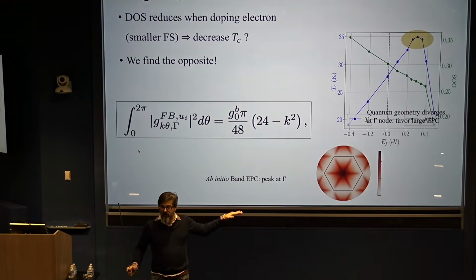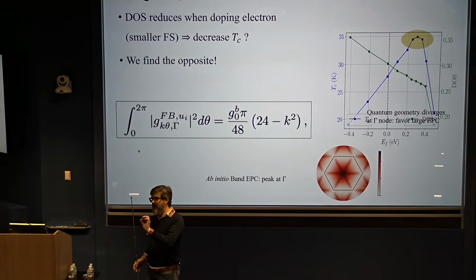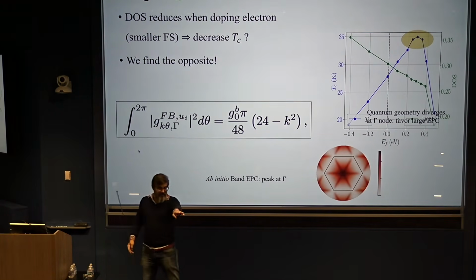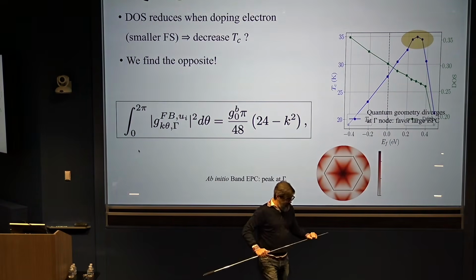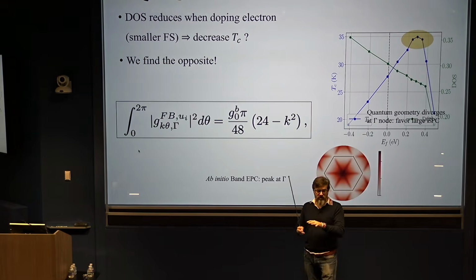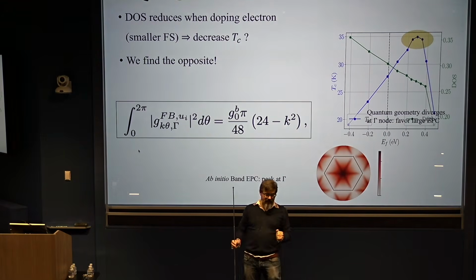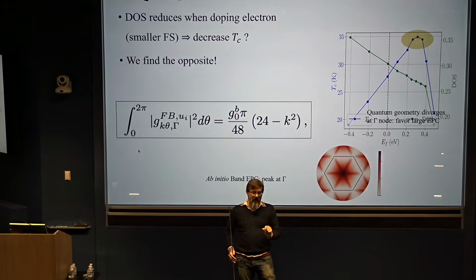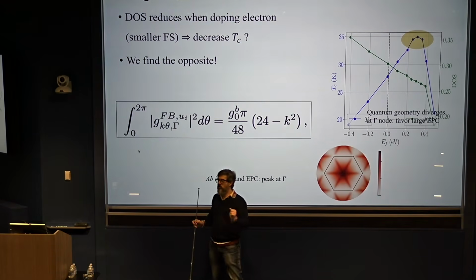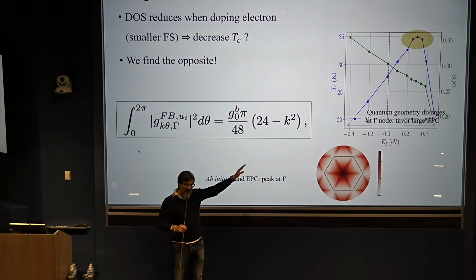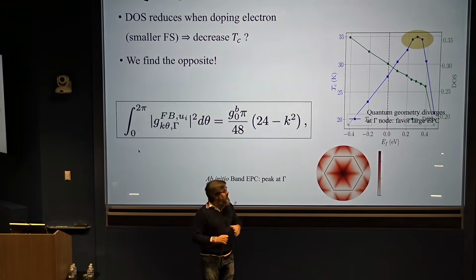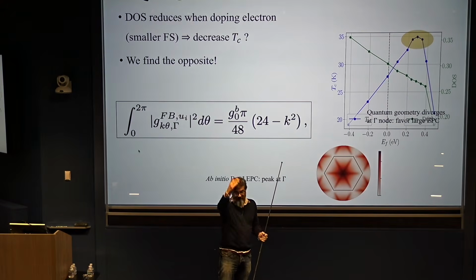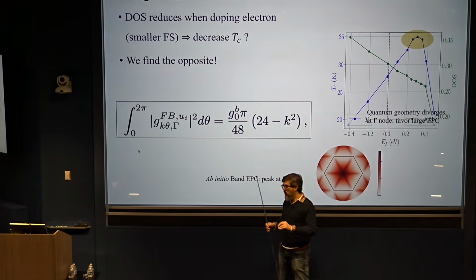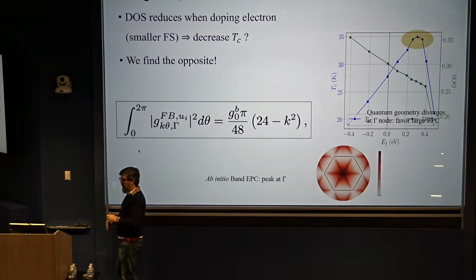So it's not the kind of doping we predict here. Now, there are experiments on thin films that we found recently, and this comes to the question that Päivi was asking in a previous conference. In those experiments, they put strain and change the Fermi surface without actually adding stuff substitutionally and messing up the band structure. In those cases, the TC does go up. It goes up to 42 Kelvin, by 3 Kelvin. So it's not as high as this prediction, but there are experiments where this happens, where you're not messing up the sample.